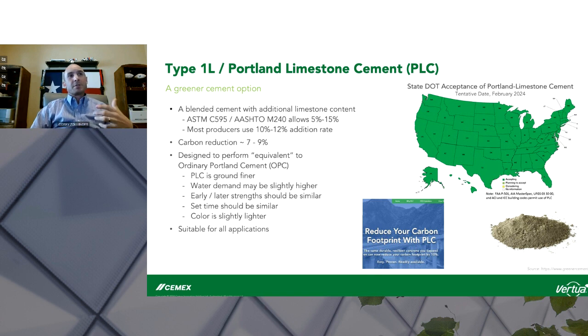So limestone cement is a specification found under ASTM C595. Historically, cement has been specified through ASTM C150. So it does require a change in your specification to allow for the ASTM C595 cements. And what it does is it moves the allowance of limestone content from 0 to 5% to up to 15% interground into your cement. It's the last process of making the cement powder.